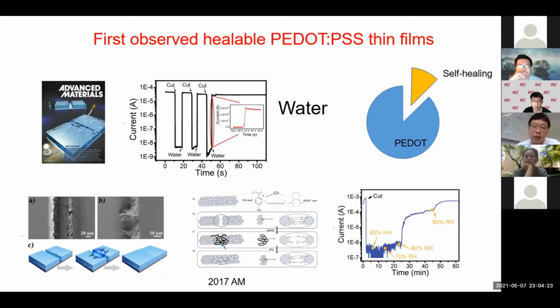Another one: for very thin, for example, 1 micrometer thick, the mechanism we use to explain is that you see this figure. So the PEDOT:PSS includes both PEDOT and PSS. PEDOT is hydrophobic, which means there's no way they can interact with water. But PSS is hydrophilic. And actually in the film, most of the part is PSS. The ratio is around 1 to 2.5, which means 2.5 is PSS.